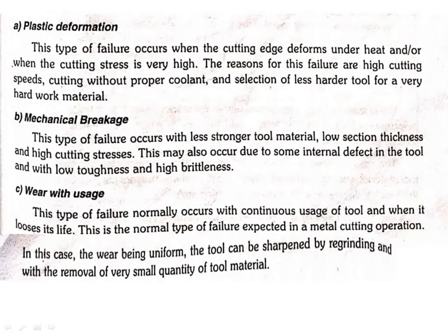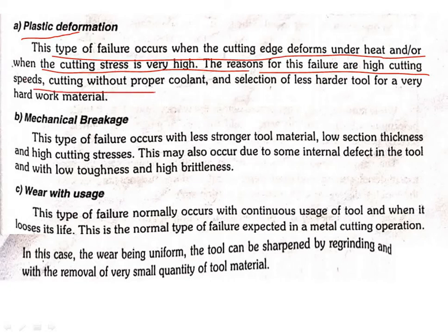Plastic deformation, this type of failure occurs when the cutting edge deforms under heat, when the cutting stress is very high. The reasons for this failure are high cutting speeds, cutting without proper coolant, and selection of a less hard tool for a very hard material.